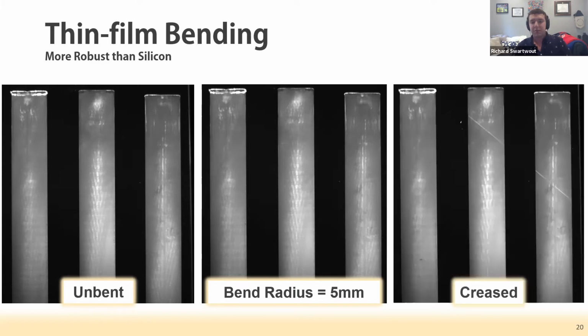It's only when I deliberately crease the system and crease that underlying plastic substrate where you see any change at all. That's the little line here, just to point it out. And it's not a crack. As you saw in the previous images, when you bend a silicon cell and a crack propagates through it, you get PL quenching, that dark spot.